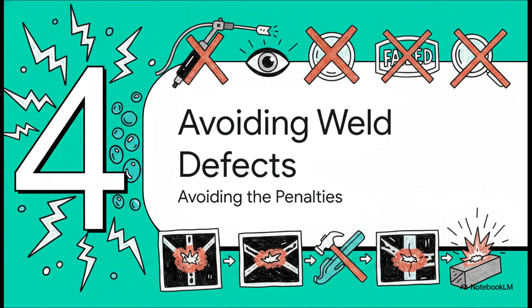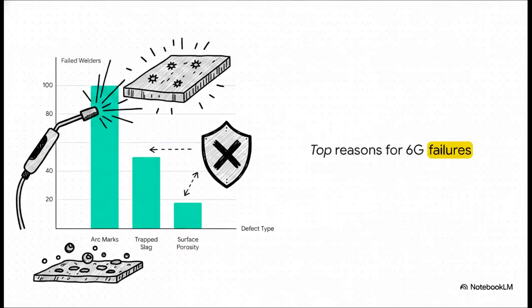Section 4. Avoiding common weld defects. Avoiding the penalties. It is time to warn you about the major penalties that lead to immediate visual or NDT, non-destructive testing rejection. Out of a recent sample of 250 test takers from one testing facility, 3 technical errors were the absolute biggest killers. Number 3 was surface porosity. Number 2 was trapped slag. But the number 1 reason people fail the 6G test? It might actually surprise you. It's arc marks.